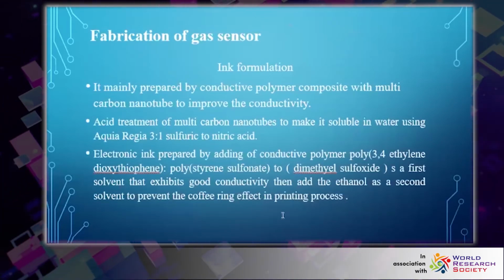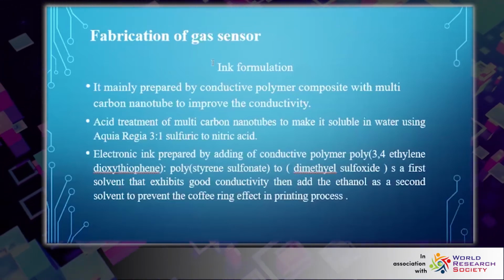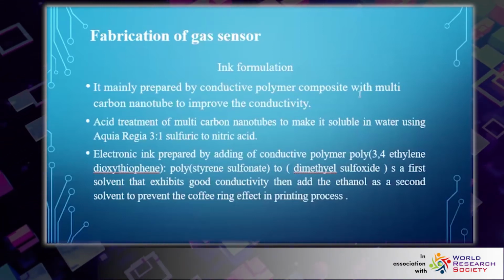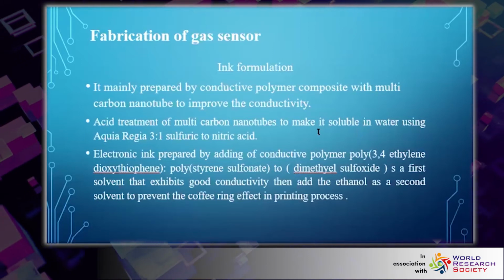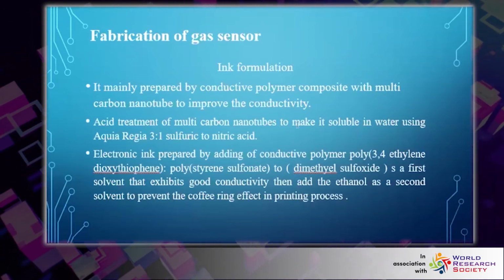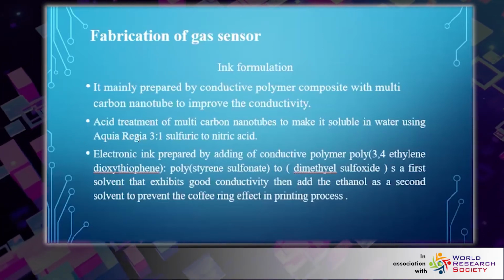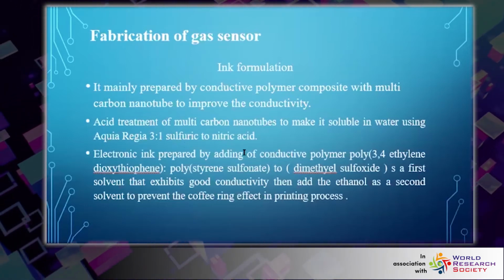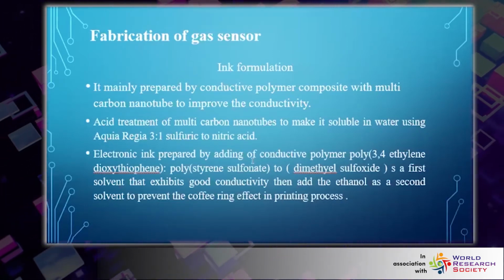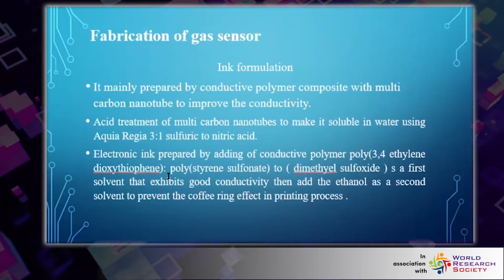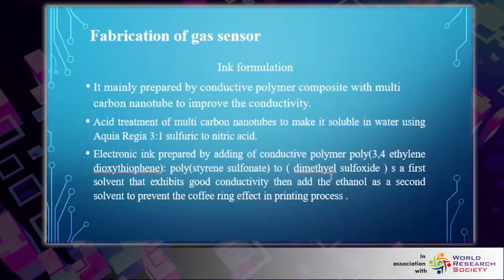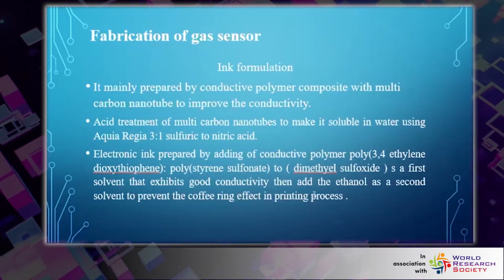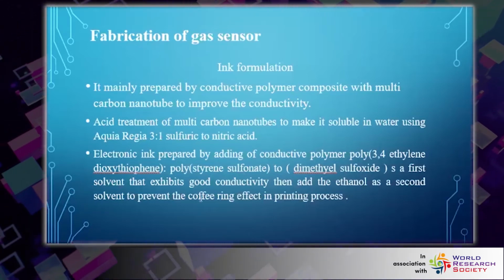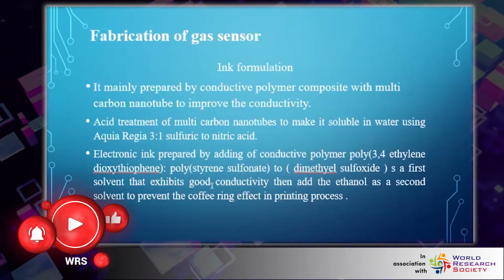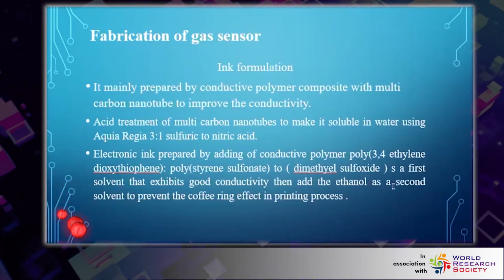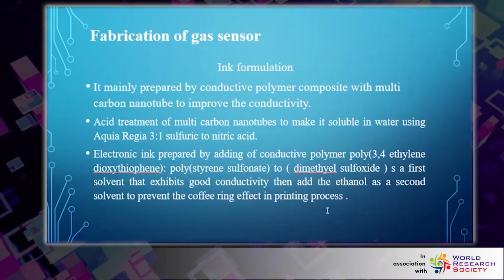Fabrication of the gas sensor: the main thing is the ink formulation. It is mainly prepared from a conductive polymer composite with multi-walled carbon nanotubes to improve the conductivity. We make an acid treatment for the multi-walled carbon nanotubes to make them soluble in water using aqua regia, 3:1 sulfuric to nitric acid. The electronic ink is prepared by adding a conductive polymer, PEDOT:PSS, to dimethyl sulfoxide as a first solvent. We use dimethyl sulfoxide as a solvent to improve conductivity, then add ethanol as a second solvent to prevent the coffee-ring effect in the printing process.